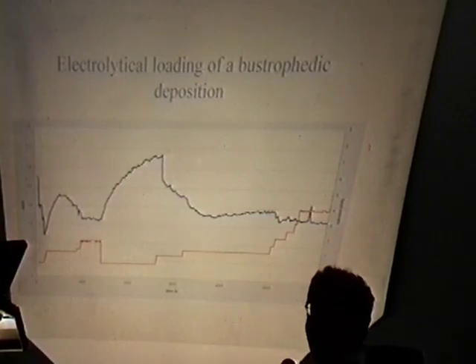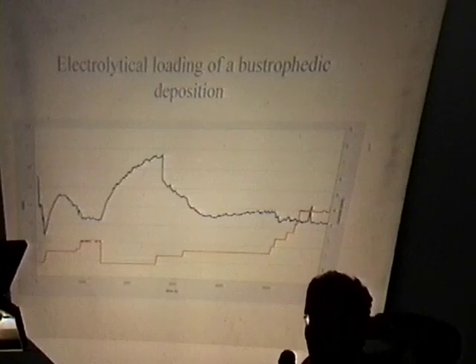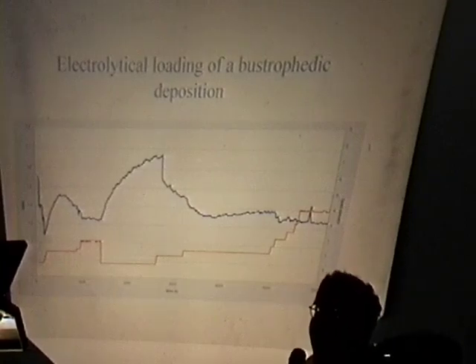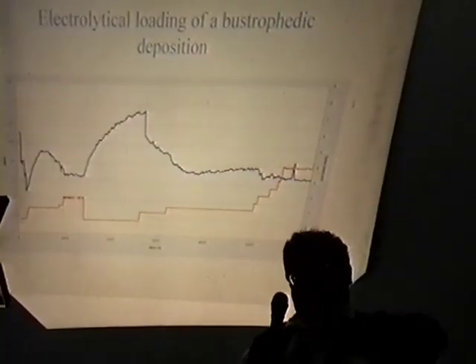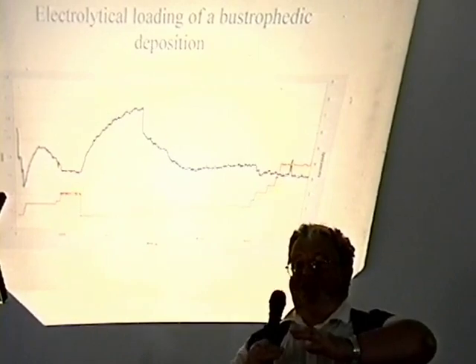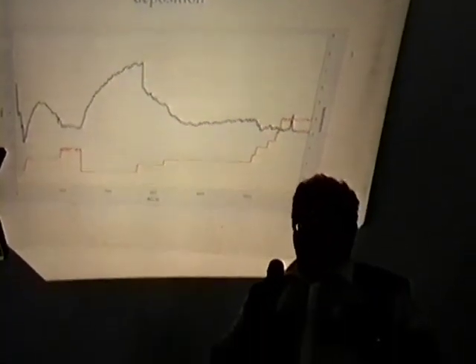We have found that in the material, in the cathode, which has been obtained by deposition, there are defects which are parallel to the surface of the deposition, and whose average distance is about 200 angstroms. This distance should be compared to the size of the coherence domain of the electrons, which at full extension are just double as a diameter. So the existence of this defect produces a compression on the volume available for the build-up of the coherence domain.